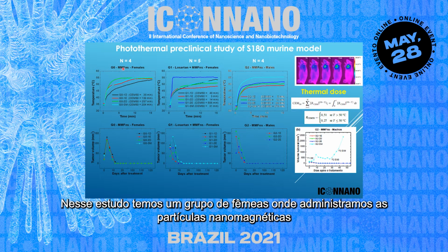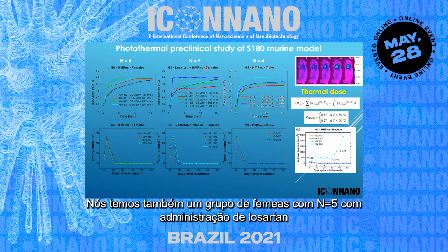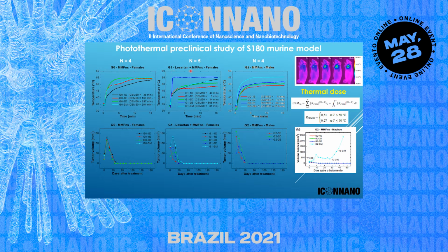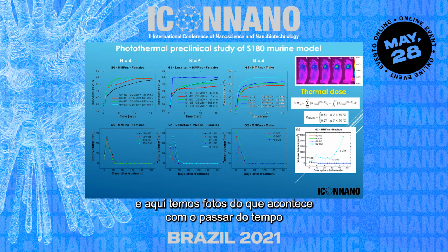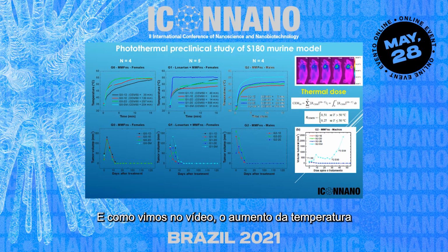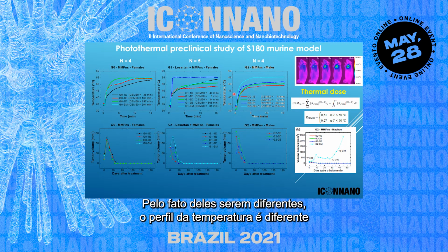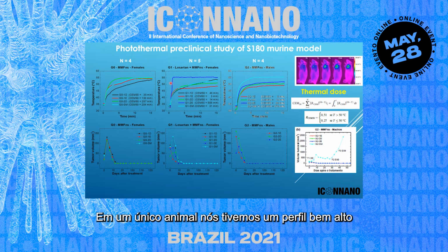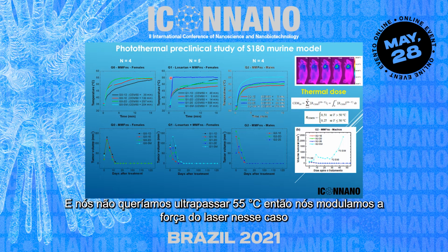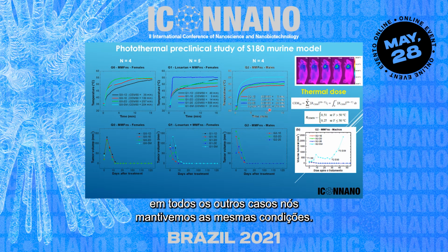So for this study, we have a group of females that we have just administered the magnetic nanoparticles. We have also a group of females with N equals 5 that had passed through losartan, and another group, but now of males of 4 animals, showing altogether 13 animals that were investigated. And here's the curve of the temperature as function of time. We have a ROI where we measure the temperature, and this is a snapshot of what's happening, increasing the time. So you're seeing, as we saw in that movie, an increase in the temperature. And this is the profile that you have for all the animals. So because they are all different, the temperature profile is different. Only one animal, we observe a very high increase here, and we didn't want to pass to 55, and we modulated the laser power in this case. The other ones was all in the same condition.